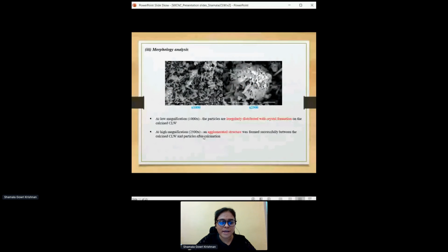In the morphology analysis, at the low magnification range, we found that the particles are in irregular distribution with crystal-like formation. But at the higher magnification, we found that the particles are formed in a cluster formation, and the small spherical shapes explain the catalyst, where the particles have been embedded on the calcined carbide lime waste.